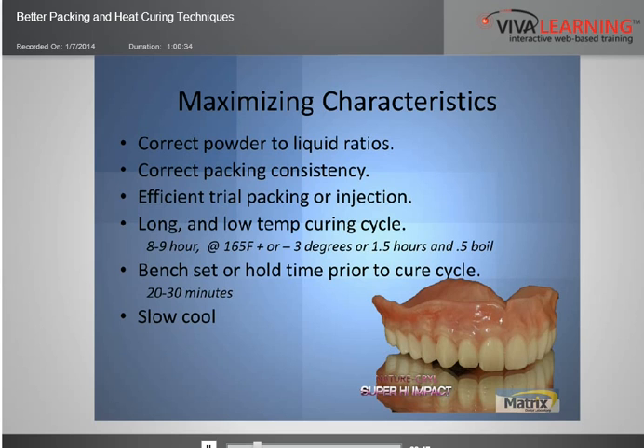Slow cool is always best because if you quicken the cool, a lot of times what will happen is you'll get shrinkage, and in effect you'll get a warpage if you're not careful. I would say in extreme measures. And extreme measures would be when people call me and say, I'm having problems with my acrylic, it seems like the fit's not as good, and then I start to review their technique and I find that the technique was that they took it right out of boil and dropped it right into cold water. You can't do that. I usually put it in lukewarm water and then for about 10 to 15 minutes, and then I add some cold water to it.